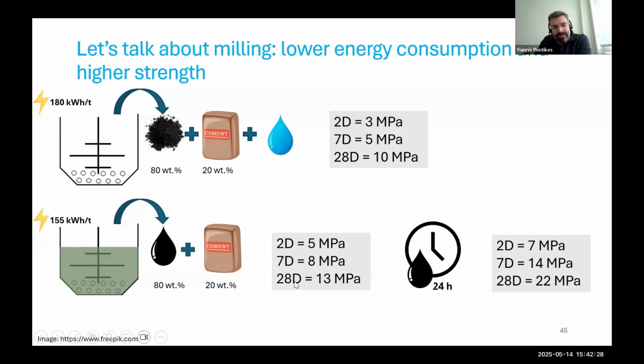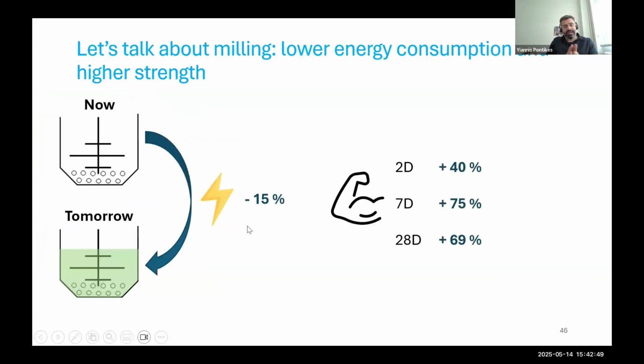Funnily enough, we also see that if we keep the slurry for 24 hours, then the performance, once we add the aggregates, is increasing. So it seems that the dissolution is happening. It's an ongoing reaction. So it would make sense if you also delay your production day. And that's interesting, because it means that you can have less energy consumption in the milling step and higher performance. And these are simple things somebody can do to make it happen.